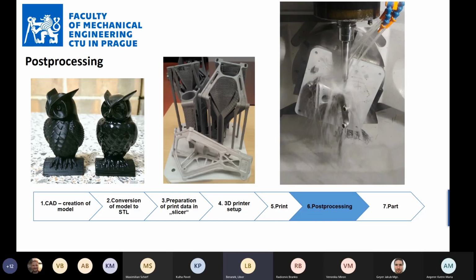You will never be within the specifications of hundredths of millimeters, 0.01 or something like this. But because the final products require this precision, because usually they are not isolated in the object or in the construction, they have to be able to fit somewhere quite precisely, you have to deal with it. And of course, even here, the orientation of the part was a little bit influenced also by the possibility to keep it on the platform during the machining, because that's another aspect of post-processing.